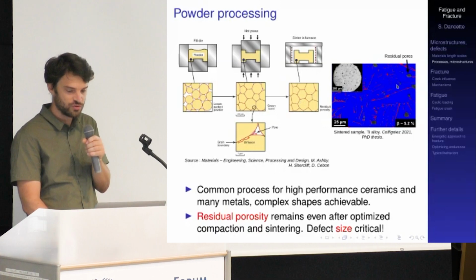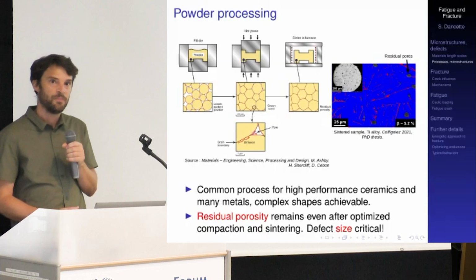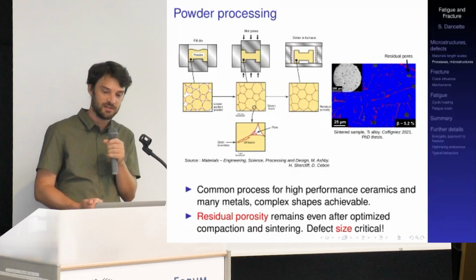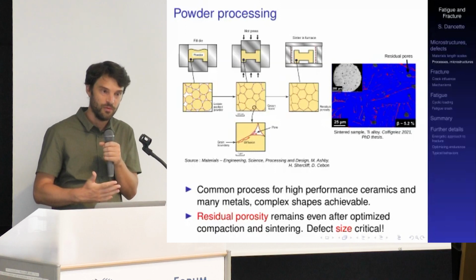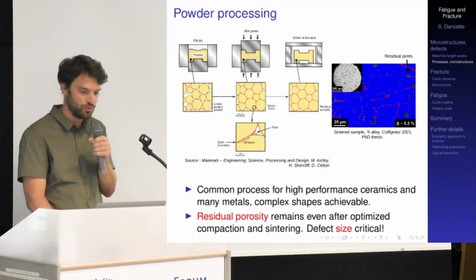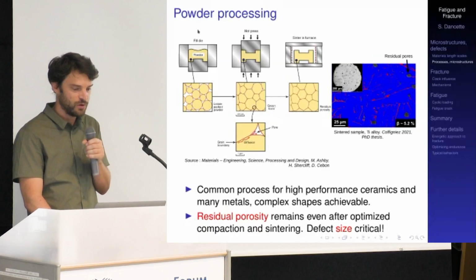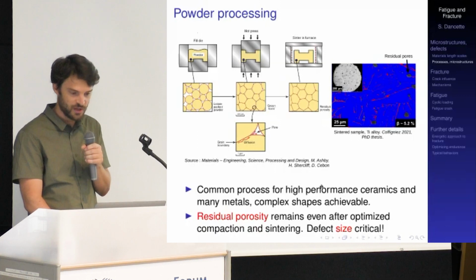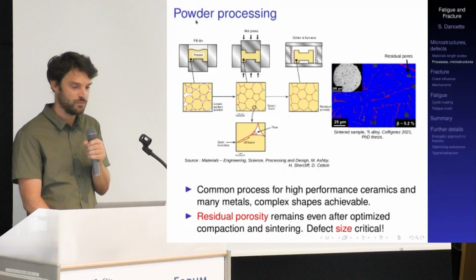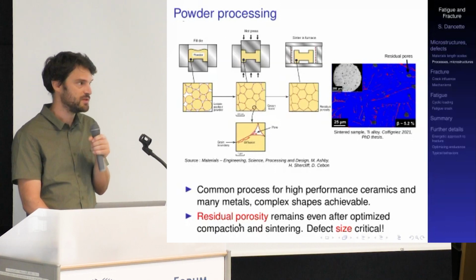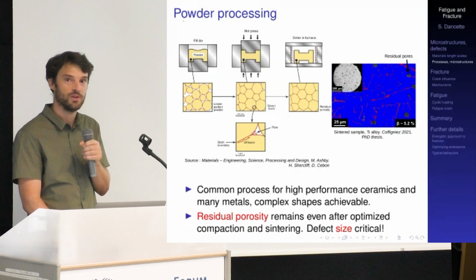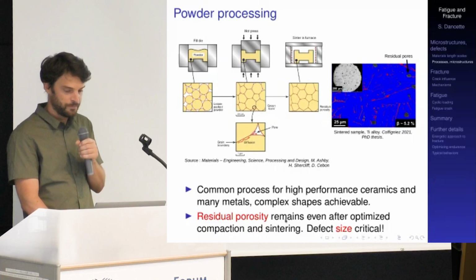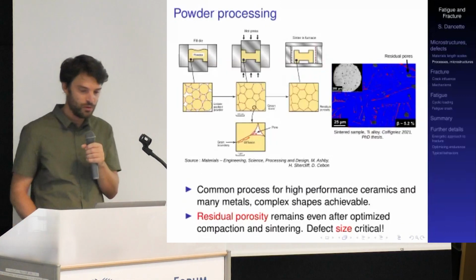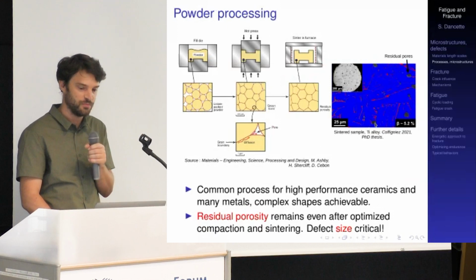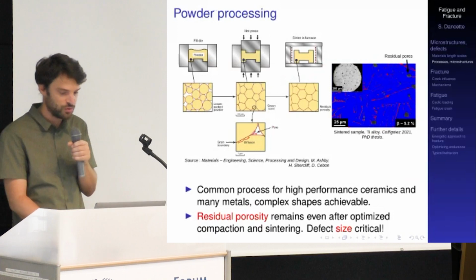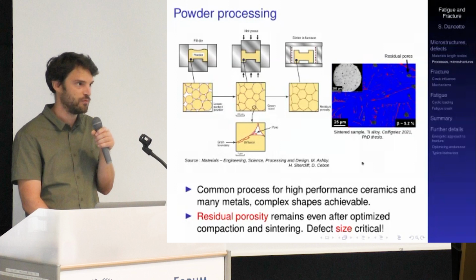These residual pores, sometimes as large as a few dozen micrometers, well, they are here in the microstructure, and they constitute potential initiation sites and potential sites for early fracture in the material during service. So we have to keep in mind that when we talk about ceramics, and especially high performance ceramics, most of the time they are obtained from that kind of sintering process, from powder processing. And there is always some residual porosity in these materials, which will have a strong impact later on during service on the fracture behavior of the material. And since ceramic materials in general are very brittle, again, very small defects such as these pores here may have a strong impact on the mechanical behavior and fracture behavior. So the size of the pores here is very critical in these materials.